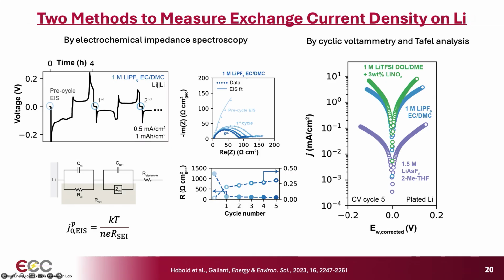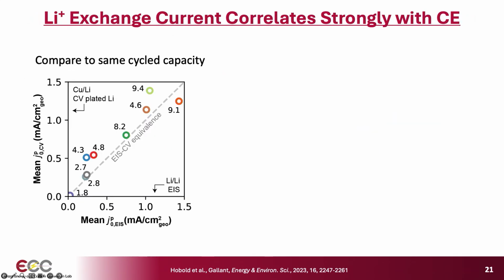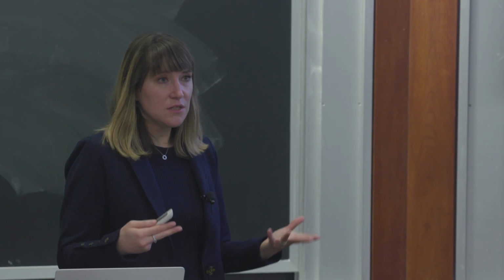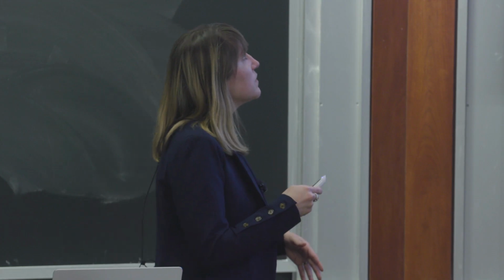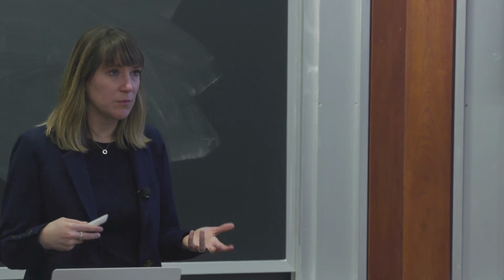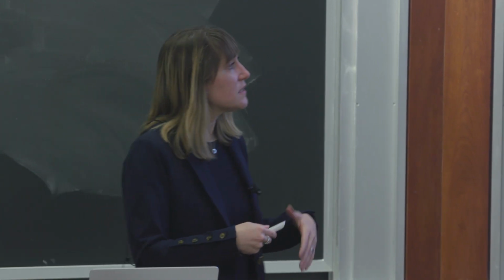And this graph now pulls together data across 9 different electrolytes, each represented by a different color. The key point is that using the 2 different methods, we could get a nice agreement between the 2, provided that we controlled for the same amount of cycled lithium in both cases. So that starts to tell us that we were measuring something that was physically real.